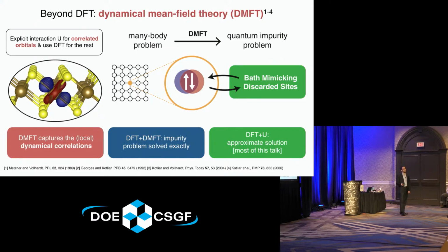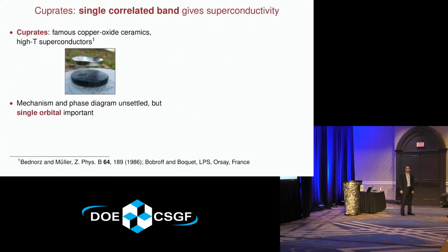So probably the most well-known class of these strongly correlated materials are called the cuprates. These are very famous copper oxide ceramic materials. They were shown back in the 80s to exhibit this remarkable property of unconventional high-temperature superconductivity. So electricity can flow with zero resistance. In addition, these show interesting levitation properties, as shown here, since they completely expel magnetic fields. And although these materials were discovered in the late 80s, the details of the mechanism of the superconductivity are still debated today and not fully settled.